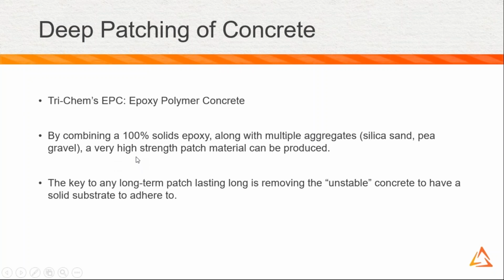When we talk about high strength, here we're down with our epoxy polymer concrete. Regular concrete is 3,000 to 5,000 psi. This patch material will be about 10,000 to 12,000 psi. So twice to 3 times the strength of regular concrete.